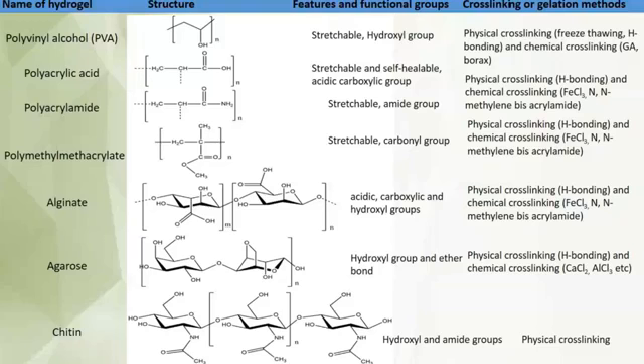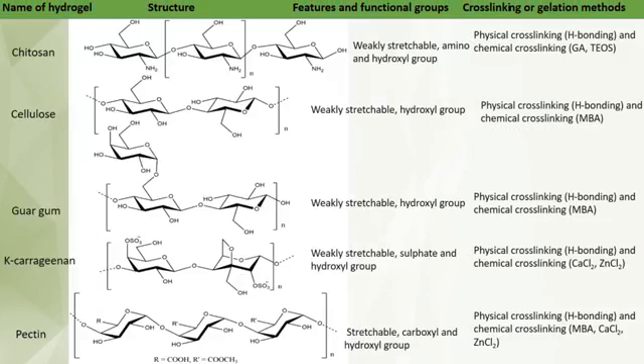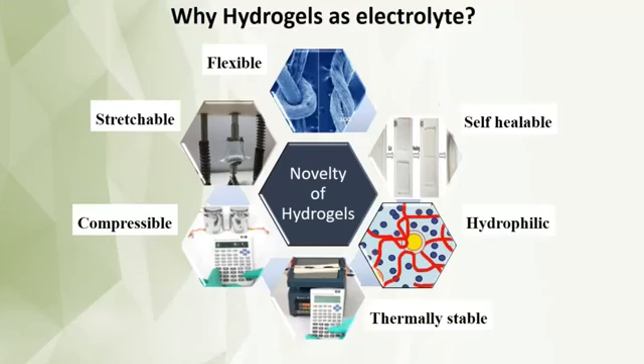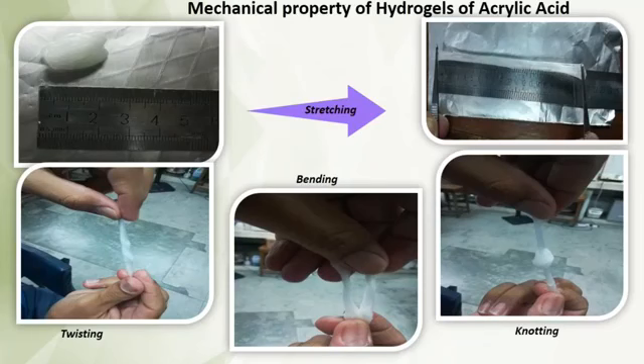For example, if you take PVA, the physical cross-linking can be done by freeze thawing or hydrogen bonding, whereas chemical cross-linking can be done by using appropriate cross-linkers. And even chitosan and cellulose can also be made as hydrogels. Hydrogel is selected because they are highly flexible, stretchable, and self-healable, and all these properties can be proposed. And hydrogel also has high stretchable properties, and we can twist them, we can bend them, and also knotting can be done with the hydrogels.